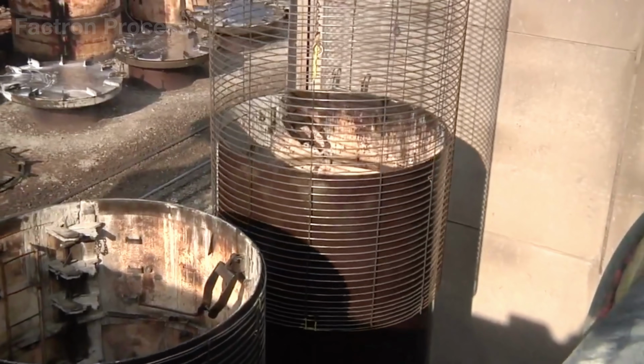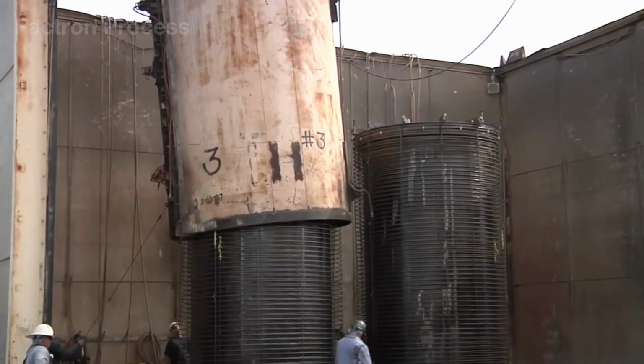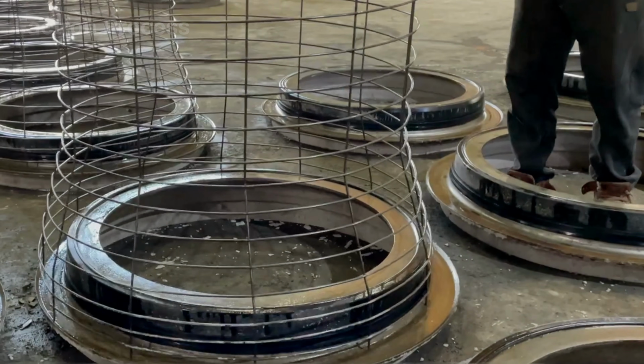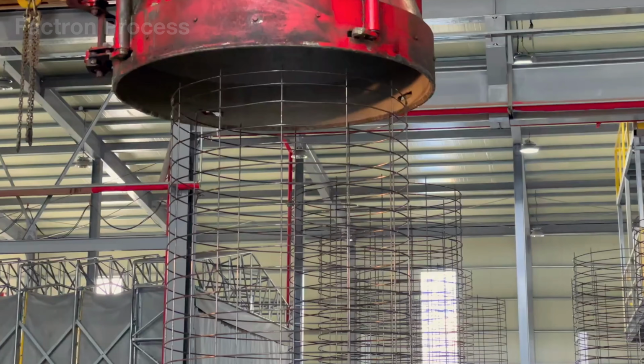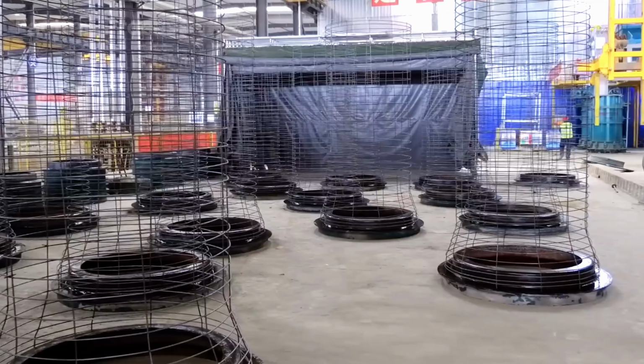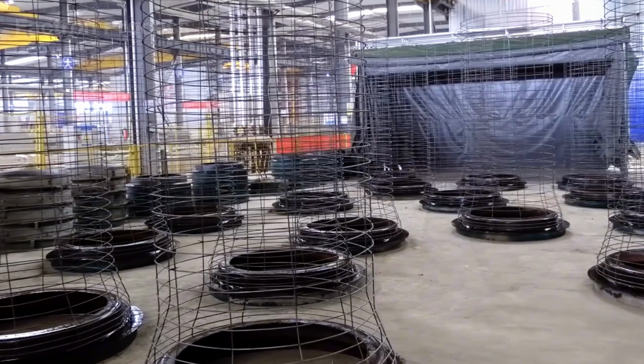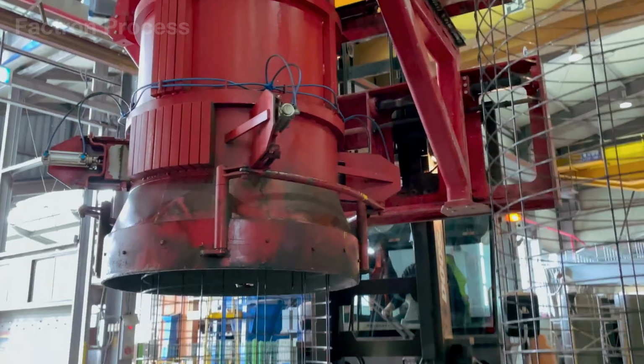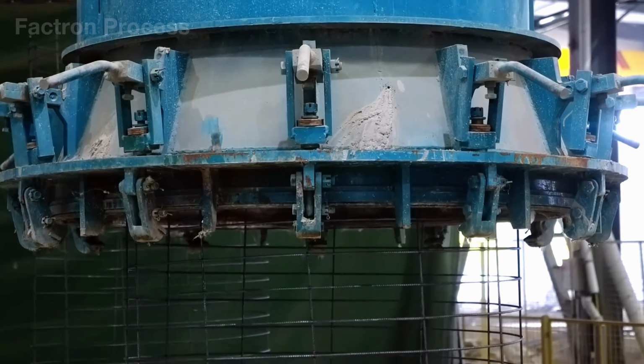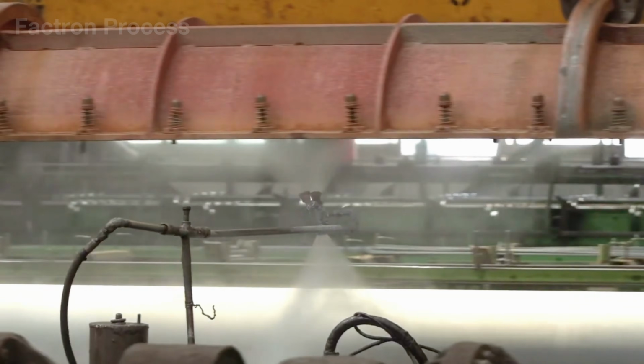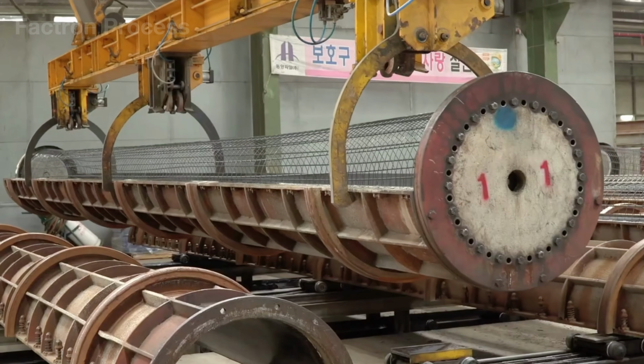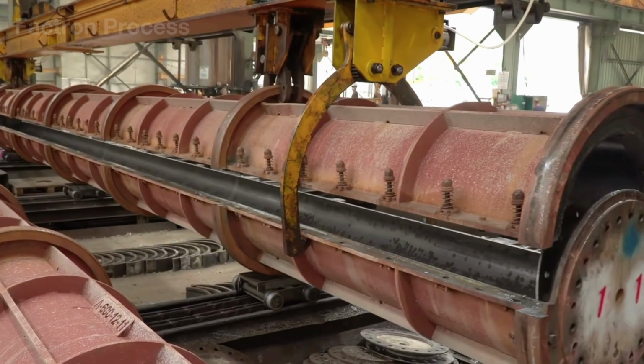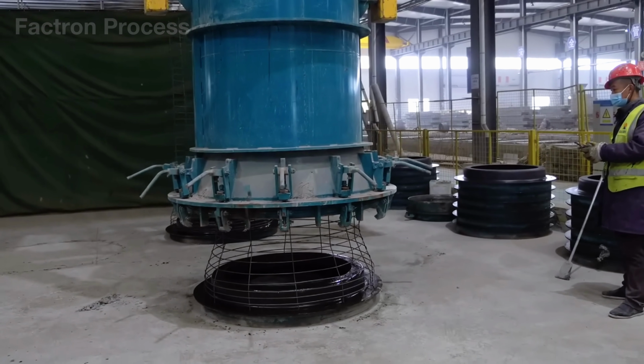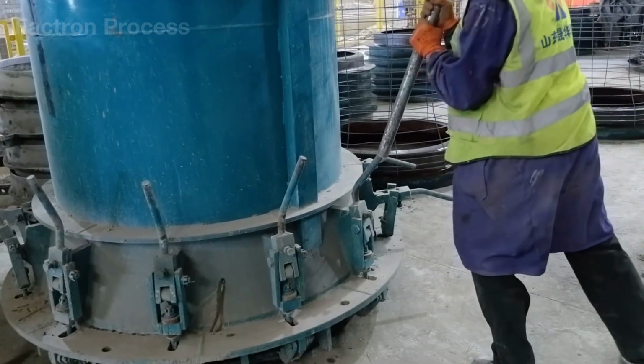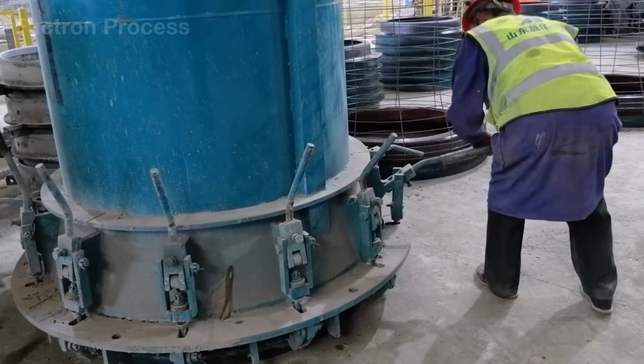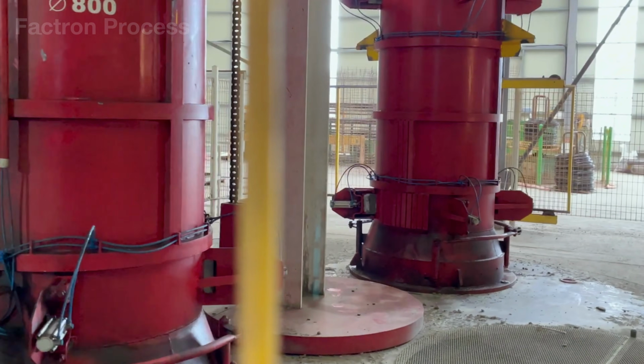Next, the base ring and the joint forming components are locked precisely into position. For pipes ranging from about 12 to 144 inches in diameter, even a slight misalignment can deform the bell end or cause a poor fit during installation on site. The steel cage is then suspended with a specialized lifting hook, distributing the load evenly along its entire length to prevent bending. Workers attach spacers around the frame before slowly lowering the cage into the center of the mold. Once the clearances are even, the outer mold is lowered into place, and mechanical pins and hydraulic locks tighten the entire mold assembly, ready to receive concrete.